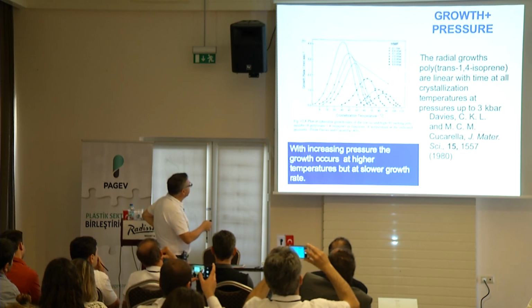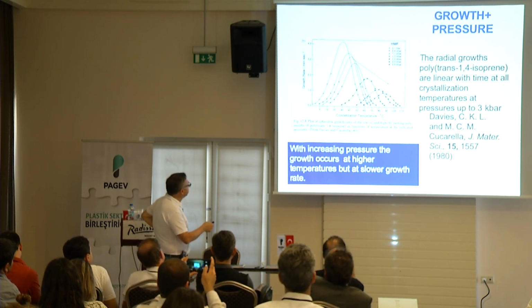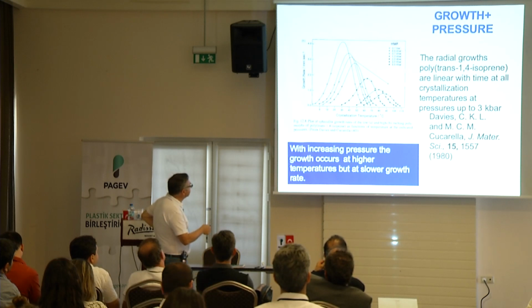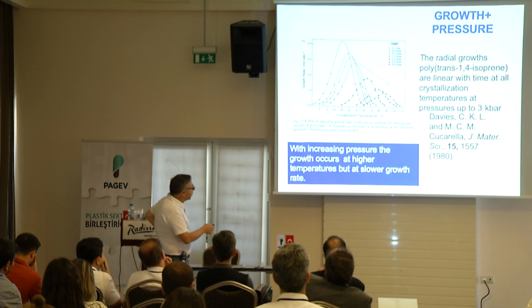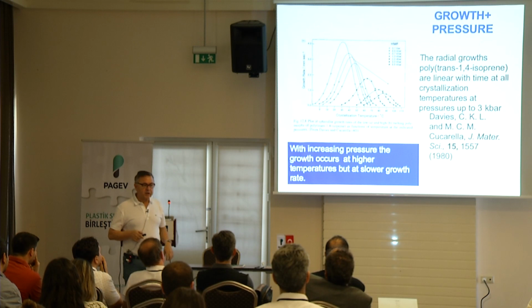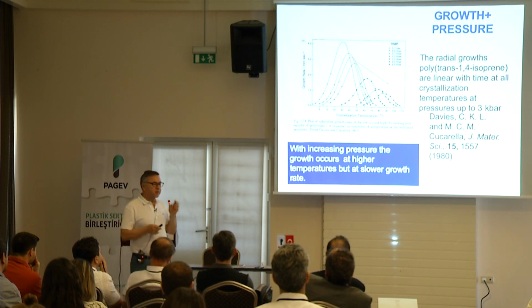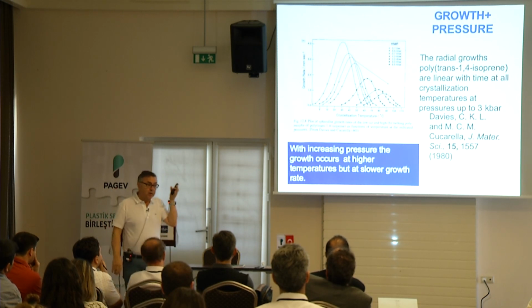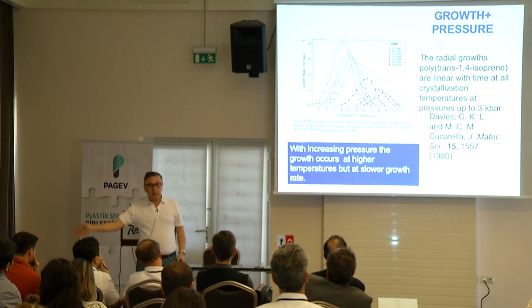This is 0.1 kbar. This is 0.5 kbar. You see that the crystallization actually shifts to higher temperatures, but the growth rates get smaller because of the pressure. So the two dominant effects: one is nucleation is faster, but the growth is slower.